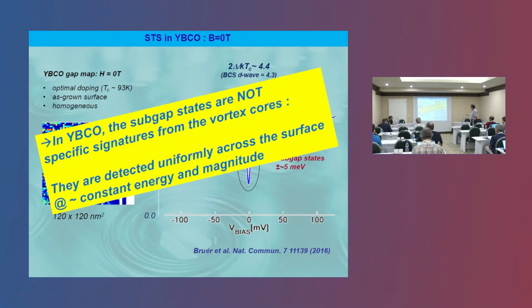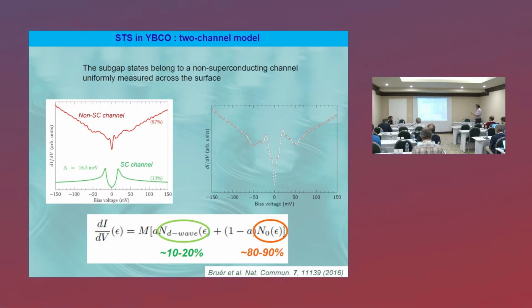So we took a very simple scheme in order to understand why we have these subgap states, which are actually detected everywhere on the surface very homogeneously. We took this model of having a non-superconducting channel, from an origin that we don't know, added to a purely D-wave superconducting channel. Our estimation provides a very small proportion of this superconducting channel, which ranges from 10 to 20% of the total current we measure. So in that picture it should be a very small signal.